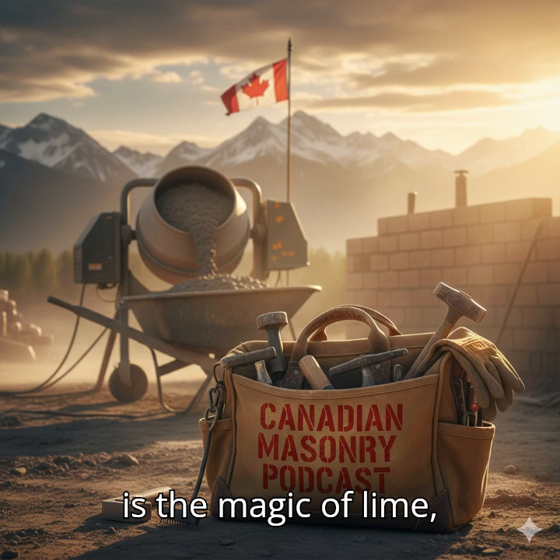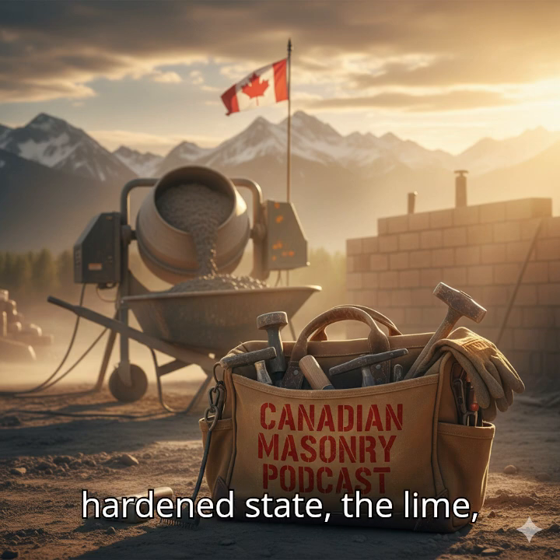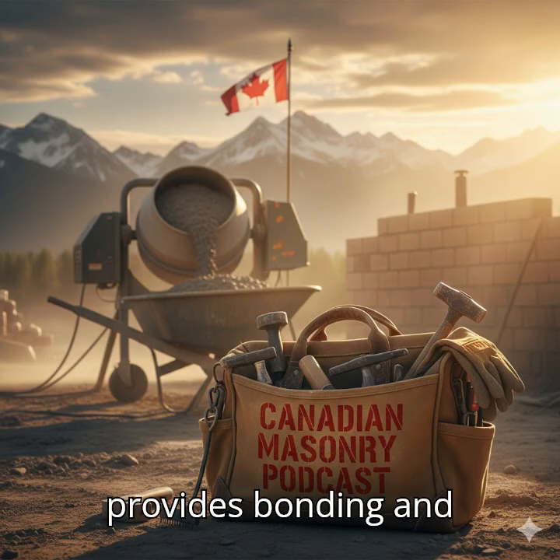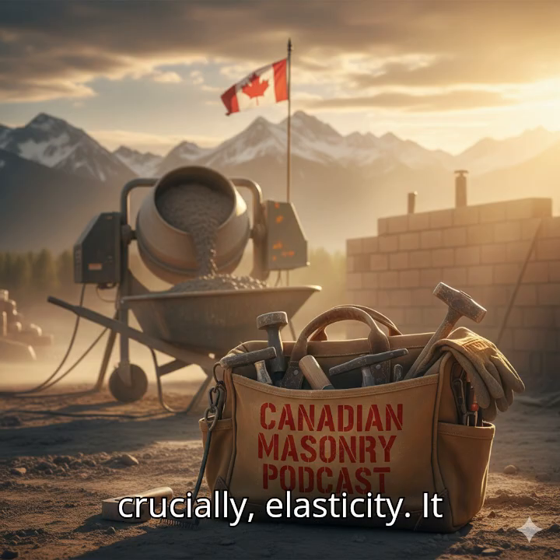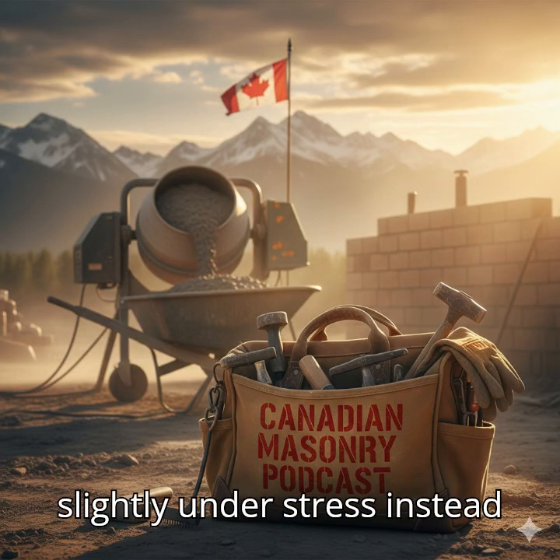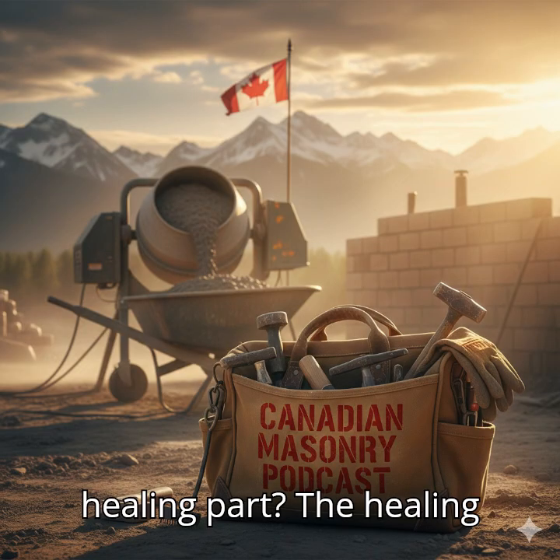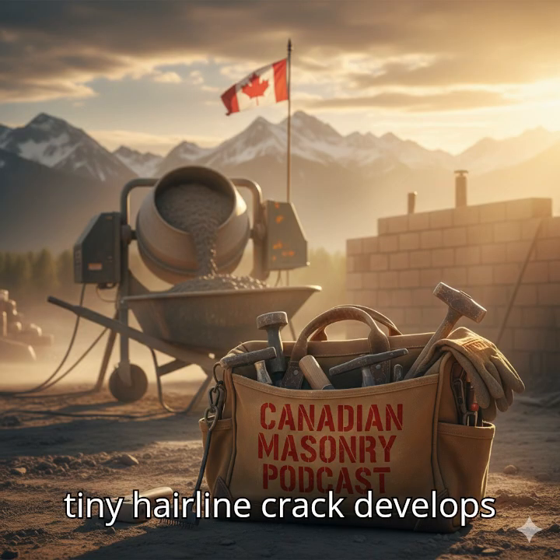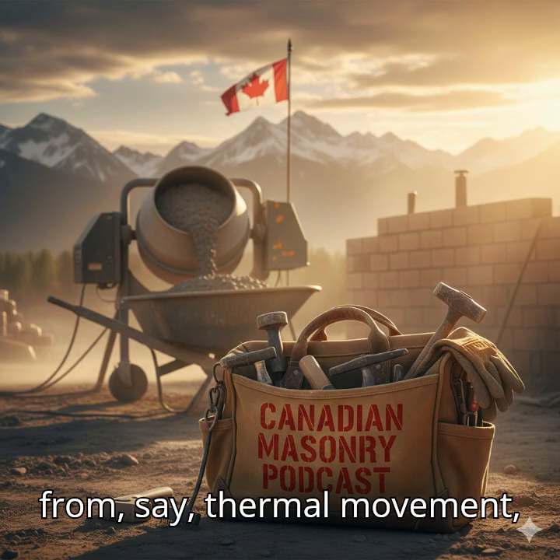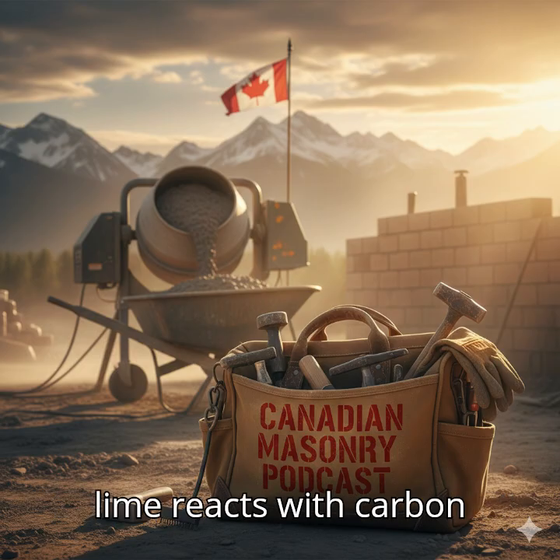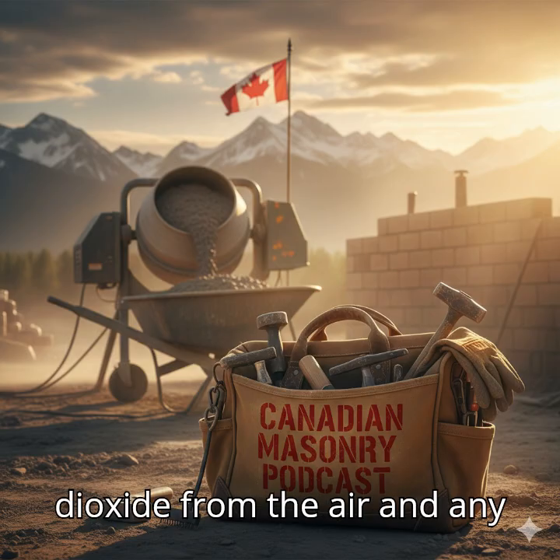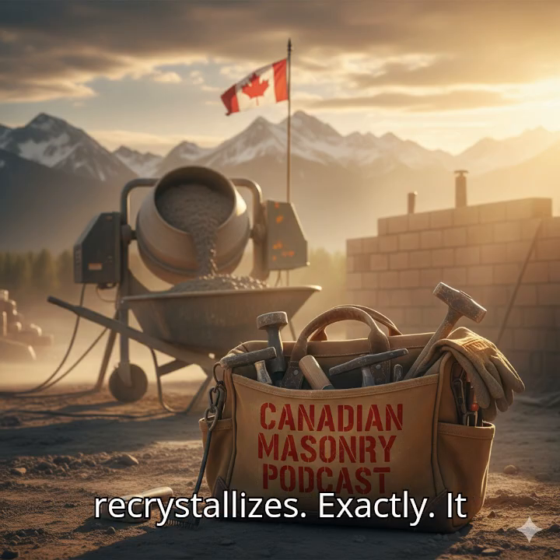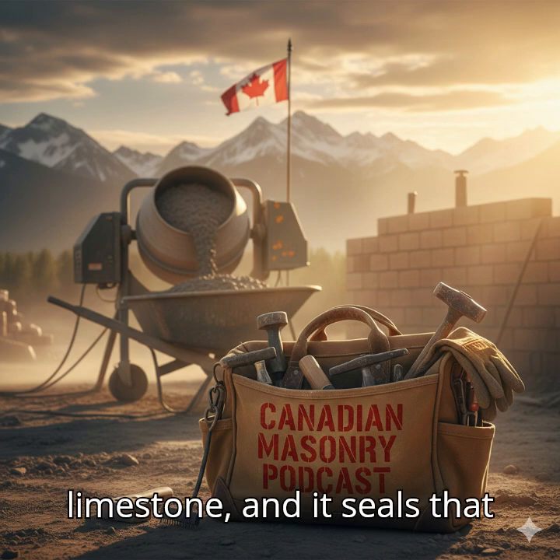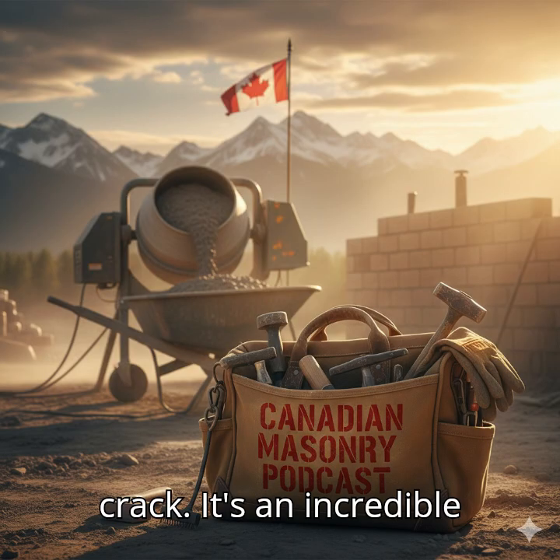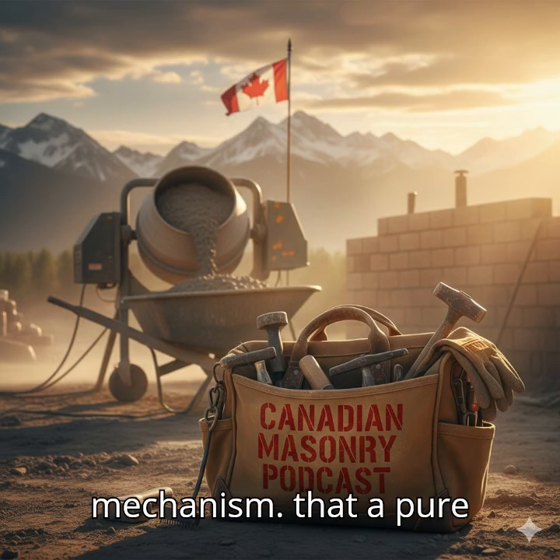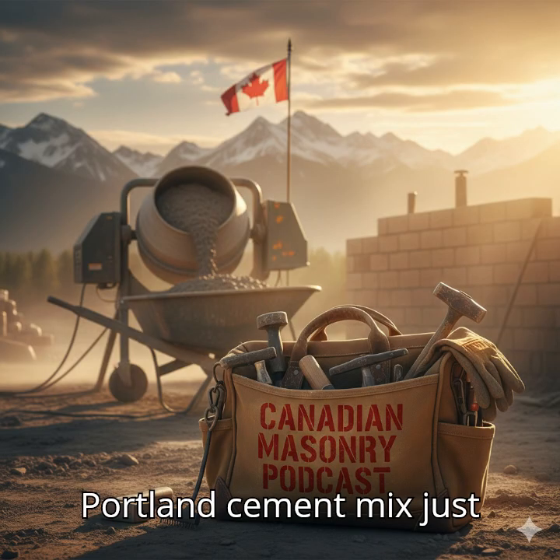Yes, this is the magic of lime, autogenous healing. In the hardened state, the lime, which is calcium hydroxide, provides bonding and, crucially, elasticity. It allows the joint to flex slightly under stress instead of just cracking. And the healing part? The healing comes from carbonation. If a tiny hairline crack develops from, say, thermal movement, the calcium hydroxide in the lime reacts with carbon dioxide from the air and any moisture present. And it recrystallizes. Exactly. It forms calcium carbonate, which is essentially limestone, and it seals that crack. It's an incredible, natural, self-healing mechanism that a pure Portland cement mix just doesn't have.